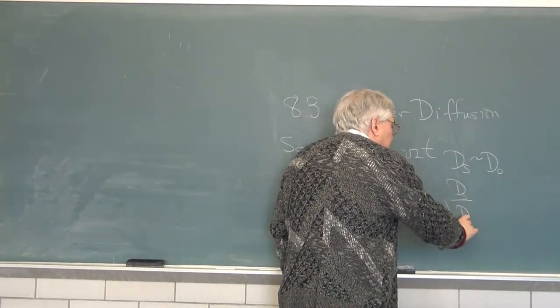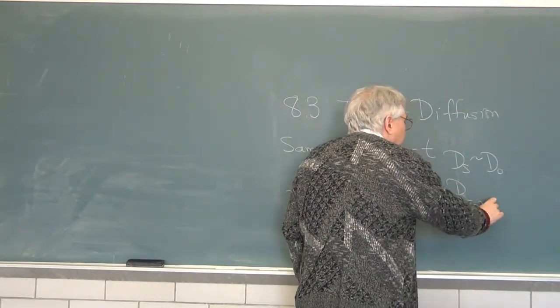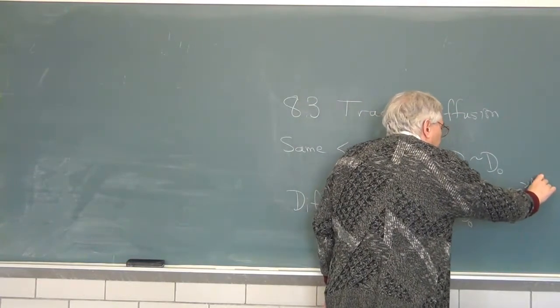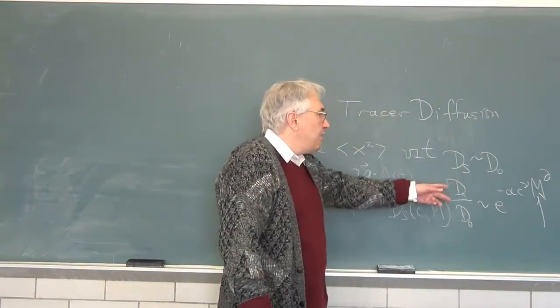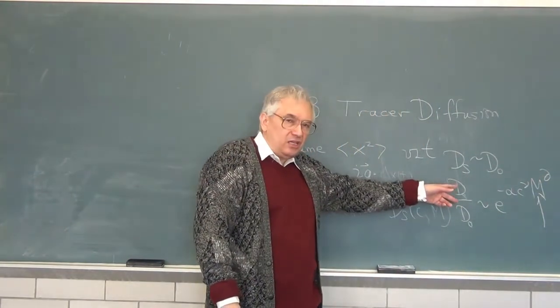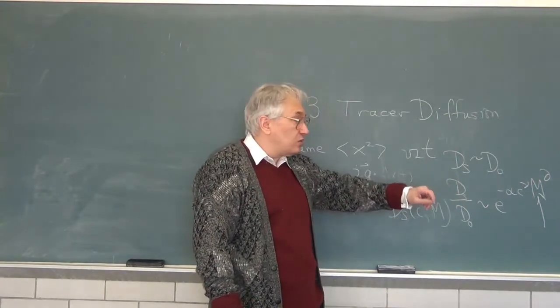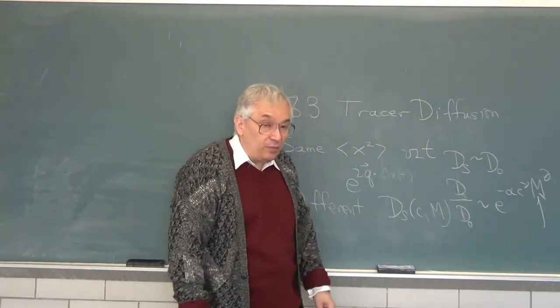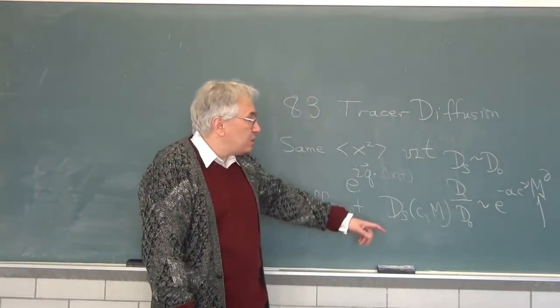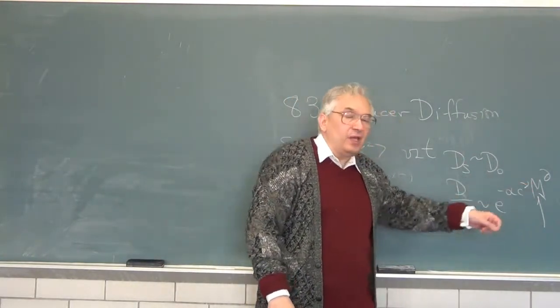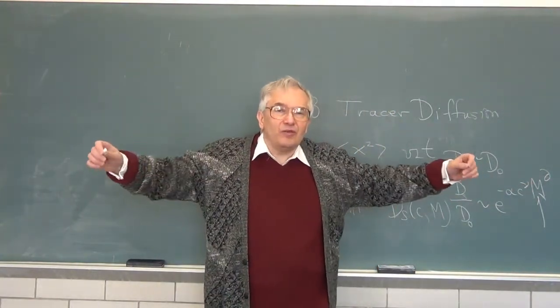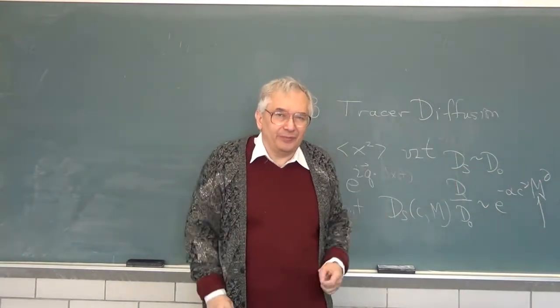If you look at D_s over D_0, the form we just talked about, e to the minus alpha c to the nu M to the gamma, there is a molecular weight dependence of how effective the solution is, on a fractional basis, at slowing down diffusion. So one possible explanation for this term is that it arises because the diffusing object is getting bigger.